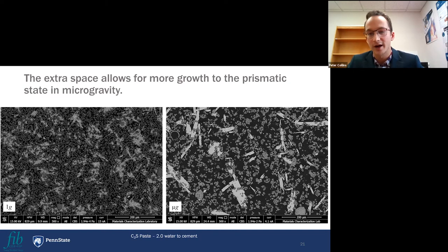Those are the light gray in this image. The darker gray is the calcium silicate hydrate. And then the black, of course, is the porosity here. And you can see the thickness in some of the CH crystals, as compared to the terrestrial gravity side, where it's just kind of growing intermingled wherever it can in between the CSH. And this illustrates the difference that gravity can have on these cements quite well.